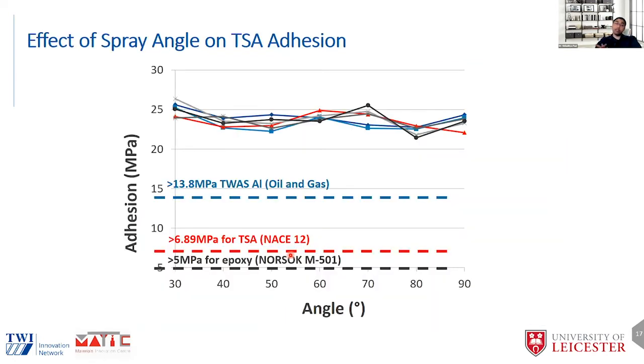So this is the result of the work where we looked at the effect of spray angle on TSA adhesion using test dollies, pull-off adhesion test dollies. On the y-axis, you have got the adhesion in megapascal. On the x-axis, you've got the spray angle in degrees. So we can see that between 30 and 90, we didn't see much variation in terms of the effect of spray angle on adhesion. It stayed around 22 to 25 megapascal, which is very typical for arc sprayed aluminium.